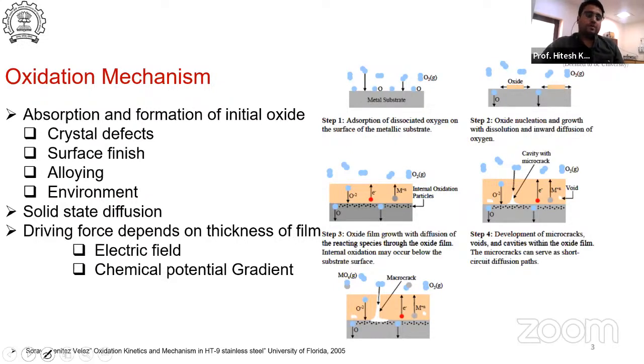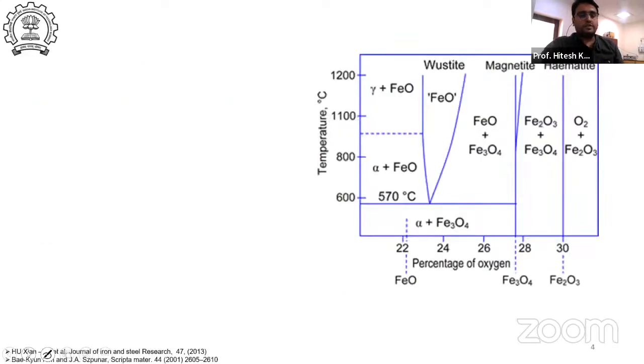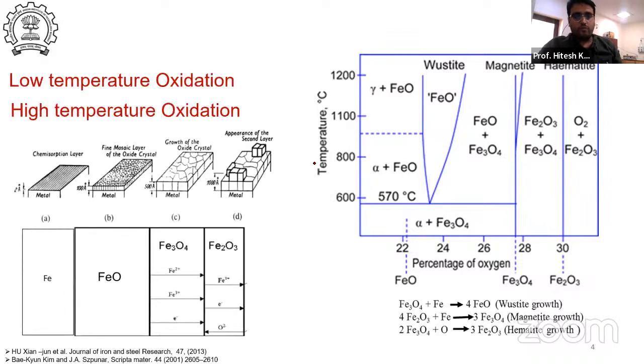When we talk about the oxidation of iron or steel, it is divided into two parts according to temperature: low temperature oxidation and high temperature oxidation. In low temperature oxidation, there are two stable phases, hematite and magnetite. The first layer formed is magnetite, and as the oxidation process carries on, the next layer formed is hematite. So starting from the substrate, the first layer is magnetite and the second layer is hematite. But above 570 degrees Celsius in pure iron, there is a eutectoid transformation where the iron substrate and magnetite react and form wustite.